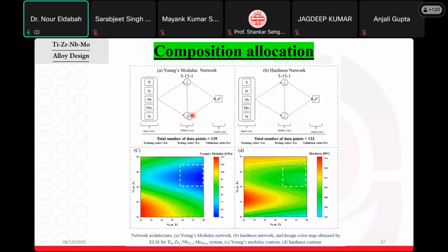These are the details of the two neural networks, one for Young's modulus and the other for hardness. We represented the predictions of these two neural networks in color contours, and we can find the lowest elastic modulus exists around the blue region here. Okay, 48% of titanium and 35% of zirconium in this region, corresponding to the same region of reasonable hardness value.